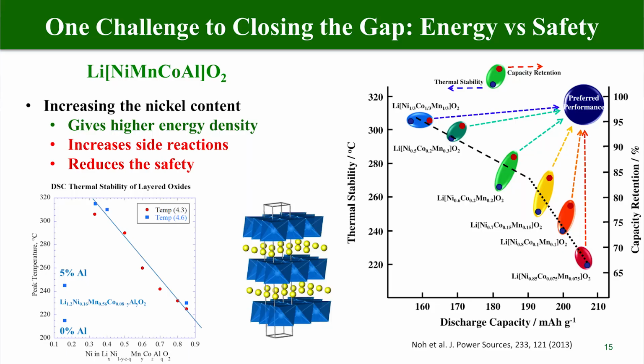So one way of closing this gap is to put more nickel in the material. This will increase the energy density, and this happened not so much to increase the energy density, but it reduced the cost dramatically. If you double the amount of nickel in there, you cut by more than half the amount of cobalt. And cobalt is the driver of the cost of these materials. But the challenge in these materials is the more nickel you put in, the more the material tends to evolve oxygen. And I'll show you some temperatures in here.